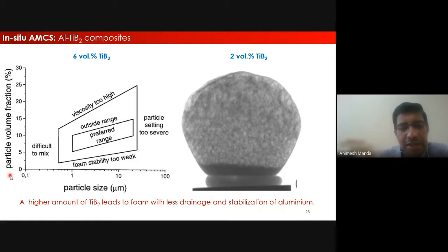For example, if you see this particular plot, particle volume fraction versus particle size, the preferred range is somewhere here. That means you cannot have a very high particle size, neither can you have a very low particle size. Always you need to follow a certain range. Again, this range will depend on the type of reinforcement we are talking about. Not only that, even the particle volume fraction has a role to play. Particle volume fraction along with particle size will have a bearing on the stability of the foam, else you will end up having drainage of the liquid metal and you will not be able to get a stable foam for different applications.